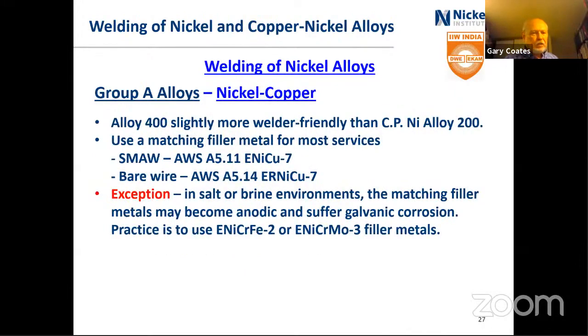The other major group A alloy is the nickel copper alloy, the Monel 400 type, and it's a little more welder friendly than commercially pure nickel alloy. It welds reasonably well with the bare wire, not so well with the coated electrode, but they've improved that a fair amount too. Now, the matching filler metal, ENiCu-7 or ERNiCu-7, is available,